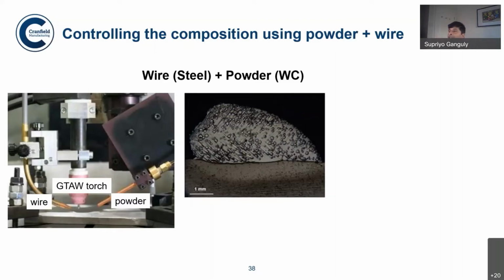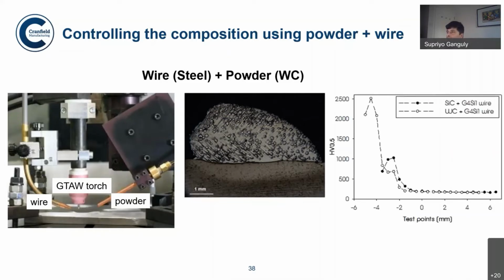This particular application was in railway brake disc, where two properties are extremely important. One is thermal conductivity, another is abrasion or erosion resistance, because when a brake disc engages with the clad, it generates a lot of heat, and unless the heat is quickly carried away, it will deform. Also, particularly in an emergency situation, it will cause a lot of frictional force at the interface, and as a result it can wear out pretty quickly. Tungsten carbide will probably give us strength in lowering the erosion behavior, or lowering the material loss. So different materials were studied. You can see here tungsten carbide with the wire gave much higher hardness as compared to when we tried silicon carbide also, and that is shown in the black.